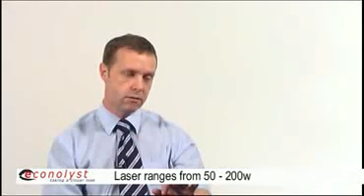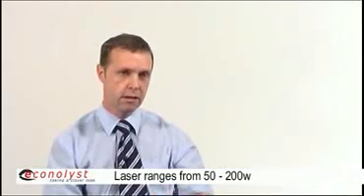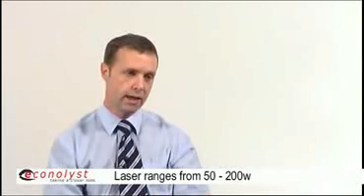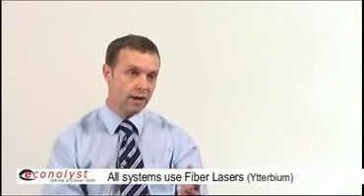Where the laser hits the metal powder, it fully melts it. What that means is we can use single component metals rather than having to alloy lower melting point metals, and I think that's probably the unique thing about the process. On the three different machines, we've got a 50 watt laser, 100 watt laser, or a 200 watt laser, all fiber-based lasers. The highest spec laser on the larger machine is 200 watts.